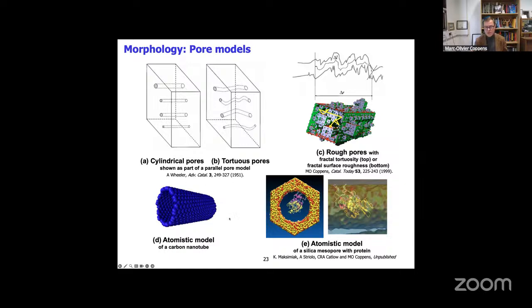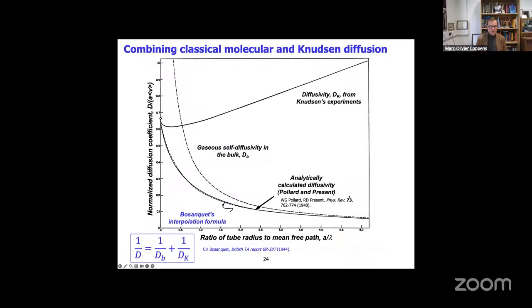And then we have, of course, atomistic models. And so, going back actually to the types of diffusion, as already mentioned in these mesoporous materials, you can have molecular diffusion within the pore space, but also often for gases, Knudsen diffusion, where the mean free path is approaching or is larger than the local pore diameter or the local chord length.